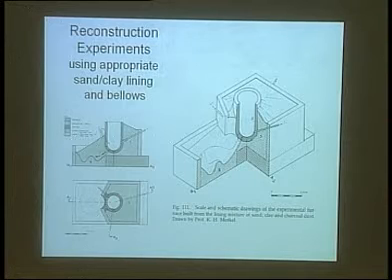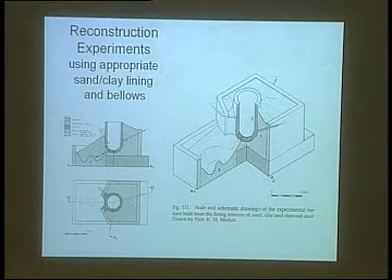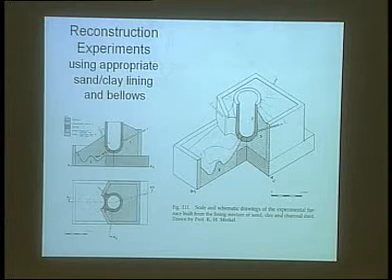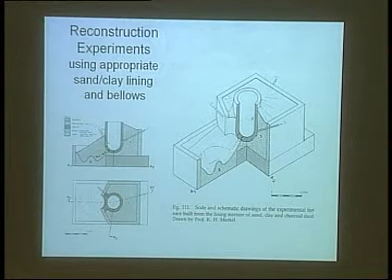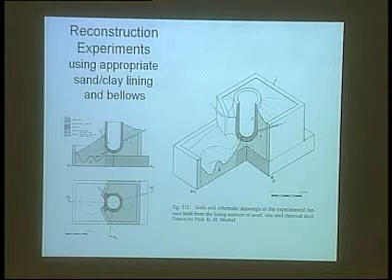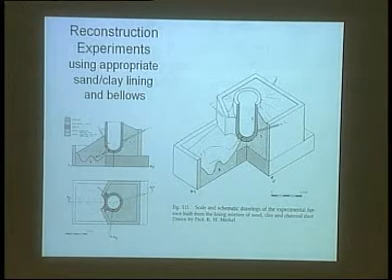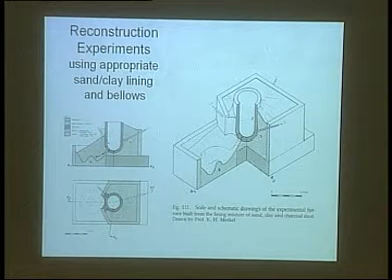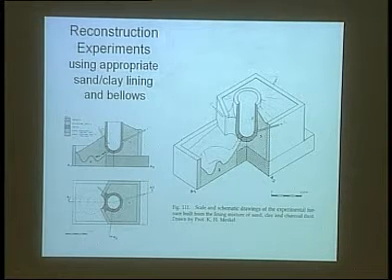We also experimented with better materials than the fire brick. We had trouble with the fire brick because we found the thermal conductivity was too high. So we did much better with sand and clay than with the modern fire brick. Well, there are different properties. Okay? So the clay refractory was a lot of sand. We used about 10% clay with the sand for higher refractory properties.